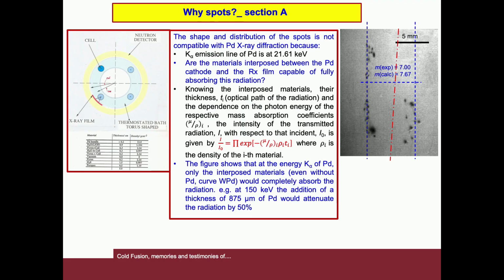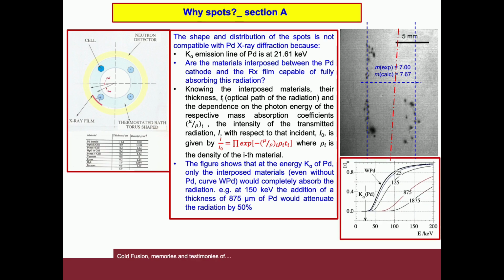Why spots, Section A. The shape and distribution of the spots is not compatible with palladium X-ray diffraction. To obtain this, a source having an energy of 21.61 kiloelectronvolts is needed, and in the system under examination, the maximum energy involved is the potential difference between the electrodes, which is of the order of 3 to 5 electronvolts. Are the materials interposed between the palladium cathode and the X-ray film capable of fully absorbing this radiation? This can be verified by making a fairly simple calculation, as long as you know the interposed materials, their thickness and their density.